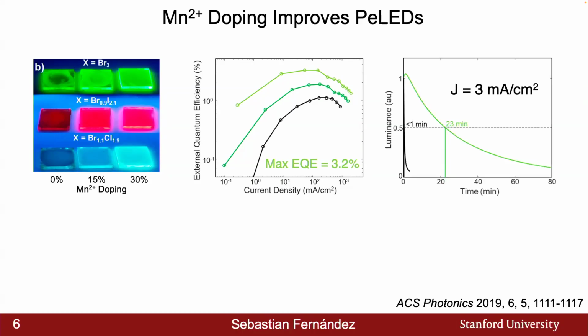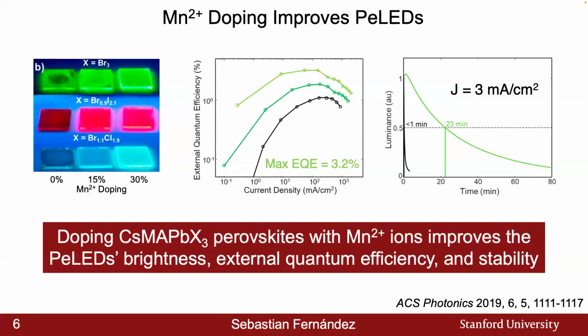For the stability, we can look at the evolution of the luminance, which is related to the amount of photons being emitted from the device. With a device that has no manganese dopants, the stability is less than 1 minute, but with 30% manganese dopants, it is increased to 23 minutes. In the aggregate, this shows that we can first increase the uniformity and brightness of these hybrid organic-inorganic perovskites with manganese dopants, but also that this translates into great gains in both the external quantum efficiency and the stability of the devices.